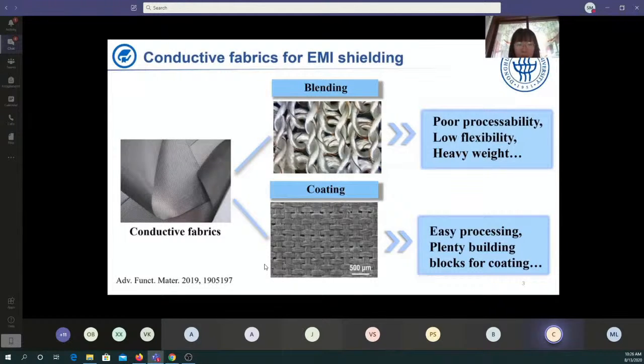There are two approaches for the fabrication of conductive fabrics. First is blending. This method uses conductive fibers such as metal and carbon fibers to blend with commercial fibers to protect human beings from EMI. But for these materials, there is poor processability, no flexibility and heavy weight because of the high stiffness and high density of the metal materials.